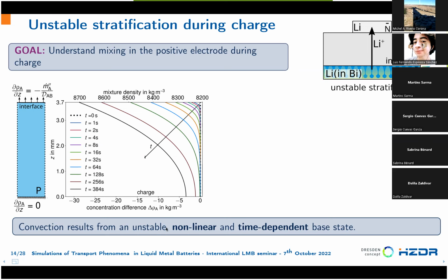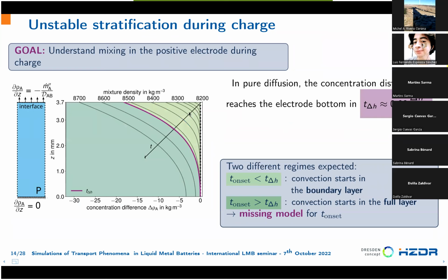And so convection starts from a non-linear and time-dependent base state. So it's not like the classical Rayleigh-Benard convection, in which we have a straight line from the top to the bottom, but these profiles are really non-linear. And already from looking at this plot, we can see that there are two regimes expected. One at lower times for a very thick layer, where we expect that convection starts when the concentration disturbance has still not reached the bottom, and one for a very thin layer, in which we expect that convection starts when the full layer is involved by the nonlinear profile.